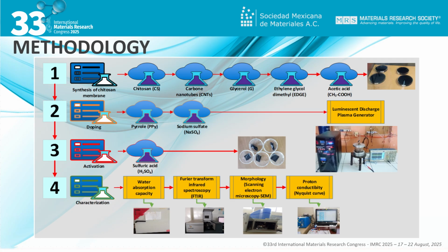In the second stage, using luminescent discharge in a reactor, the Chitosan membranes are placed in a prepared sodium sulfate solution. The reactor is connected to the plasma discharge source and adjusted so that it and the reactor enter resonance, thereby achieving polymerization of the membranes. The voltage supplied by the source is 1.0 kilovolts and 0.5 amperes for 60 minutes. After polymerization is complete, the membranes are rinsed with deionized water and left to dry.